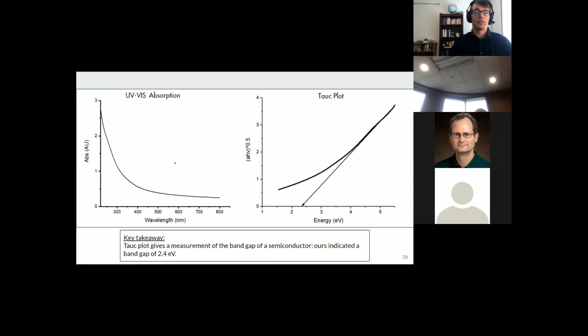The left figure represents the UV visible absorption plot of the silicon carbide nanocrystals, and the right figure represents the associated Tauc plot, which, when extrapolated to the x-axis, shows a band gap of just under 2.4 electron volts for these nanocrystals. This agrees well with the generally accepted bulk band gap of beta silicon carbide, which is 2.36 electron volts. Also, we're currently measuring some smaller particles, which we now see exhibit some quantum confinement properties as well.